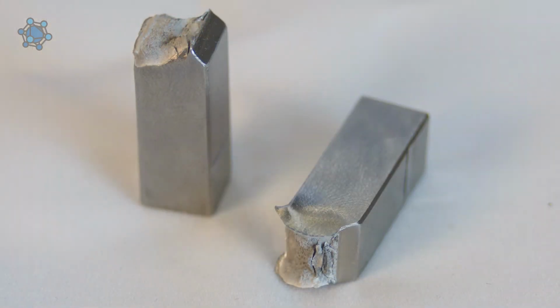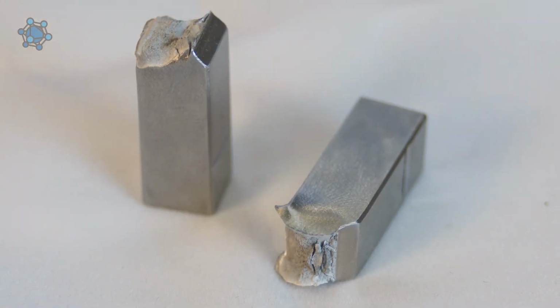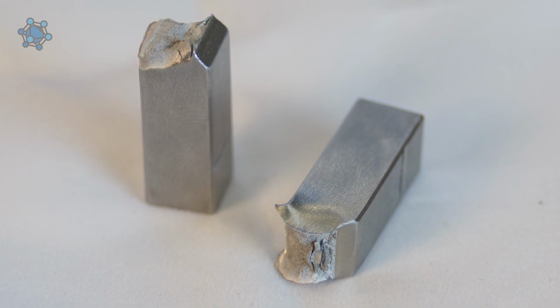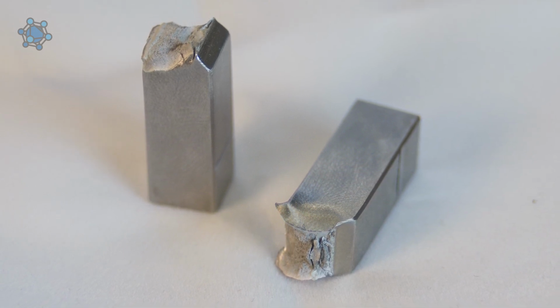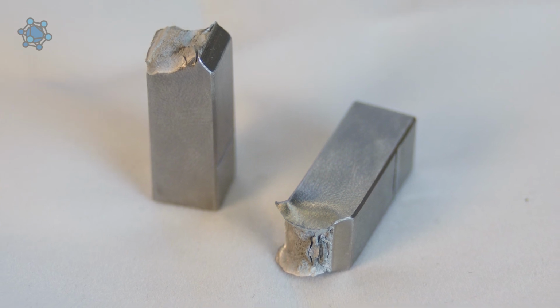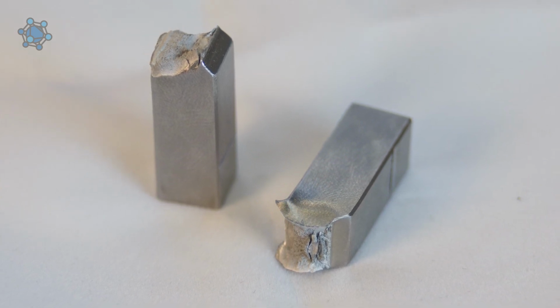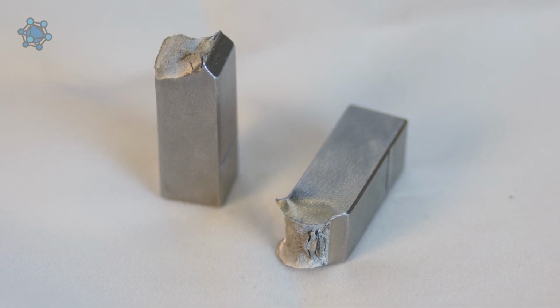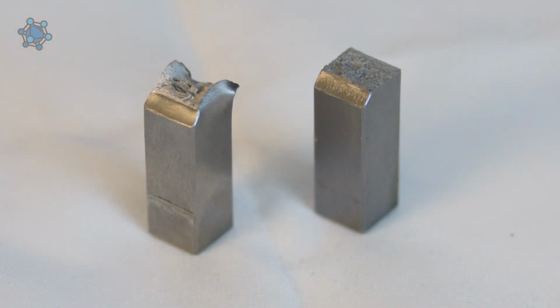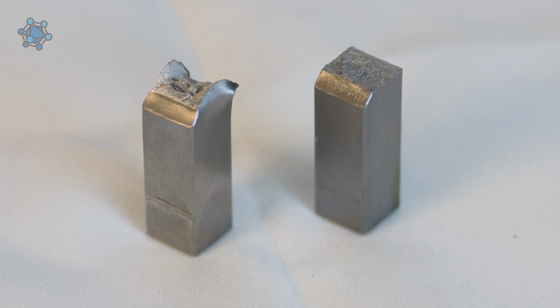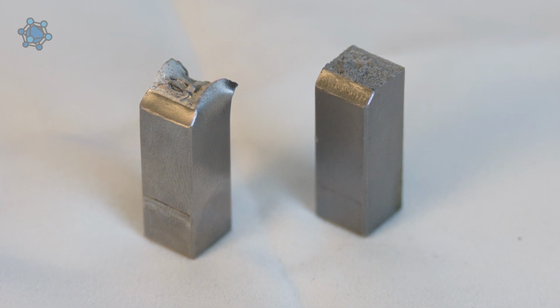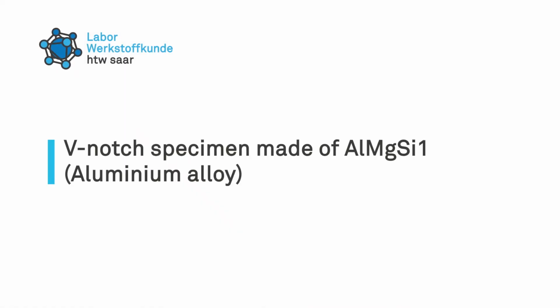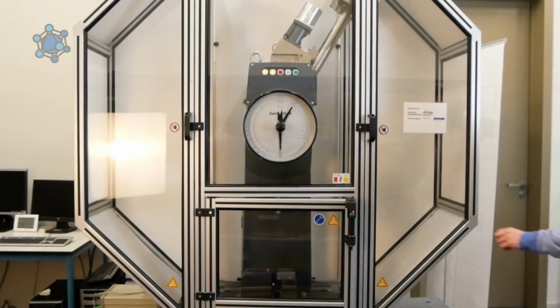The second specimen is also broken into two parts, but the fracture surface shows a clear deformation. It has been peeled open, so to speak. There is a great zone of plastic deformation, meaning that the hammer can even push the specimen between the supports before reaching final rupture. A direct comparison shows the clear difference. The stainless steel absorbs significantly more impact energy than the C45, showing a tough, highly ductile behavior in the Charpy Impact Test.